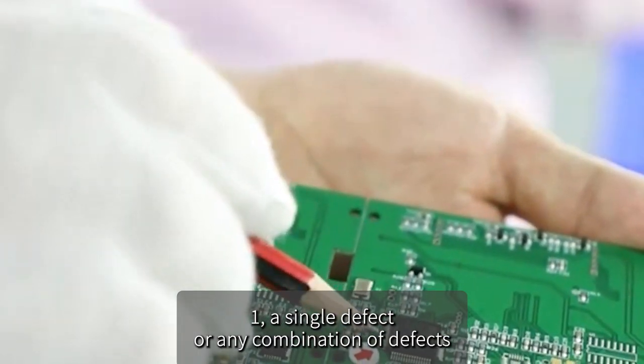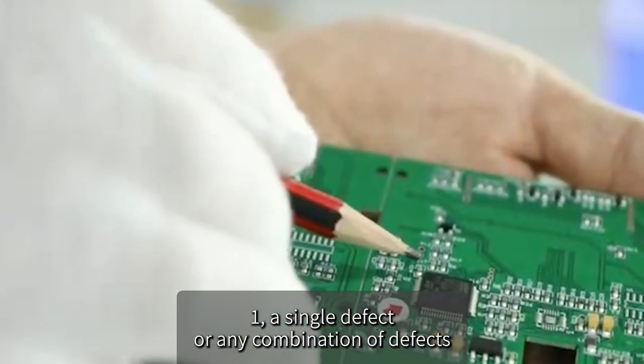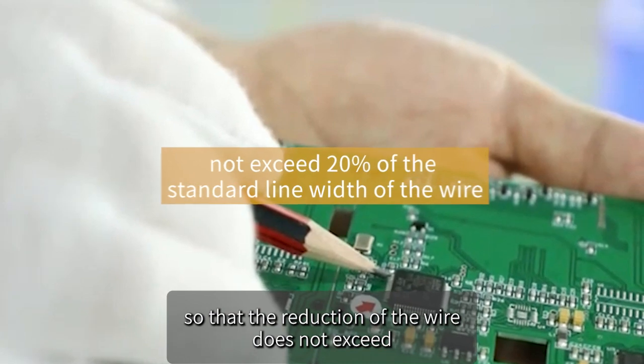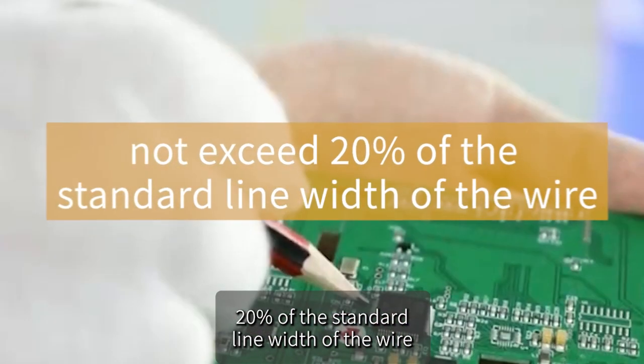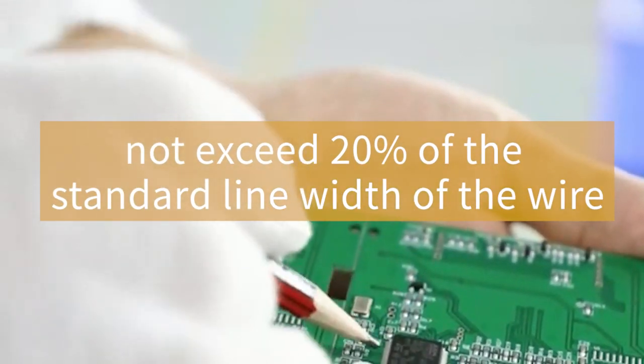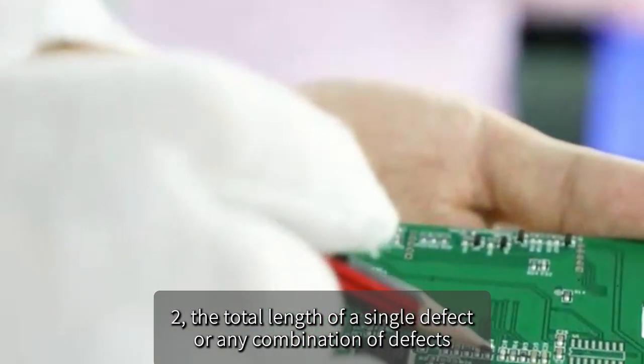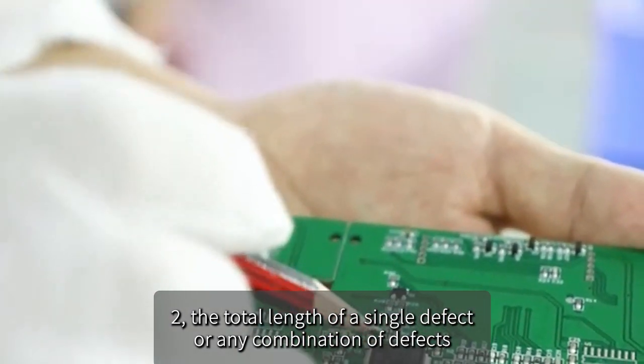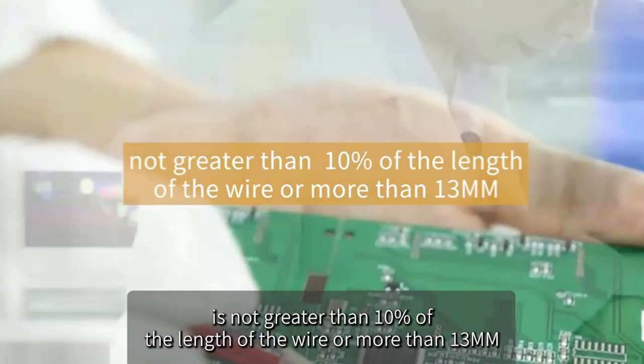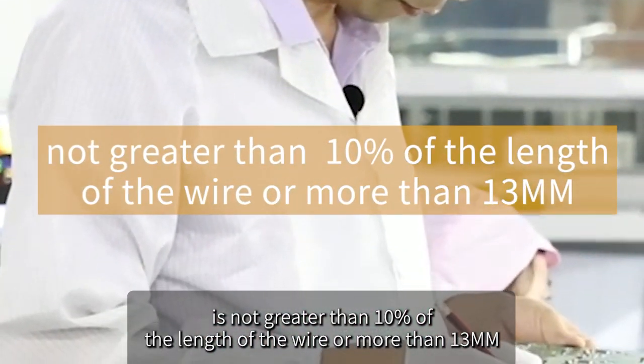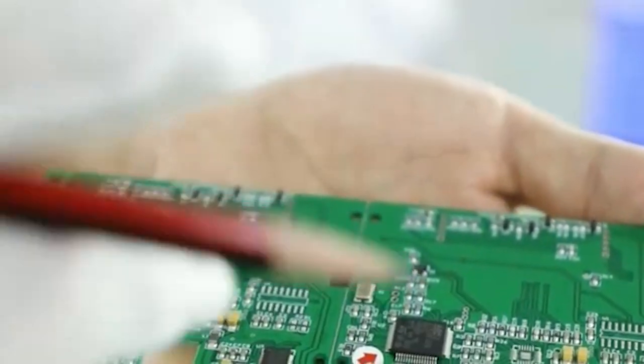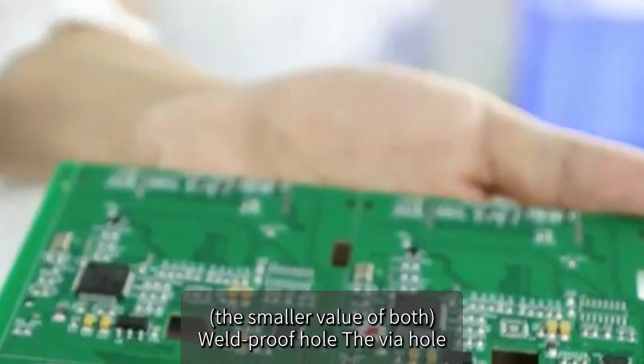1. A single defect or any combination of defects so that the reduction of the wire does not exceed 20% of the standard line width of the wire. 2. The total length of a single defect or any combination of defects is not greater than 10% of the length of the wire or more than 13 mm, the smaller value of both.